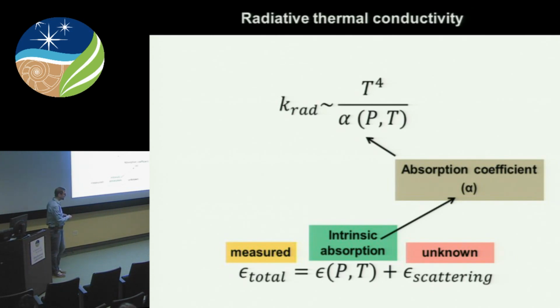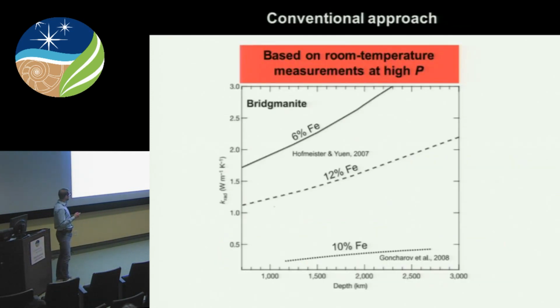So the way we evaluate radiative thermal conductivity is in fact pretty complex, but what I want you to know is that radiative conductivity is inversely proportional to the absorption coefficient, which can be constrained by our optical absorption measurements. So what we actually measure is the total extinction coefficient, which is composed of the intrinsic absorption within the mineral on the electron levels of the mineral, plus scattering effects on grain boundaries or defects that you may have in your crystal. This factor has usually been assumed equal to 0 because it's very difficult to constrain for diamond anvil cell experiments. However, radiative conductivity is also proportional to temperature to the power of 4, which means that radiative conductivity is hugely sensitive to temperature. And this is the very reason why it shoots up in the thermal boundary layer.